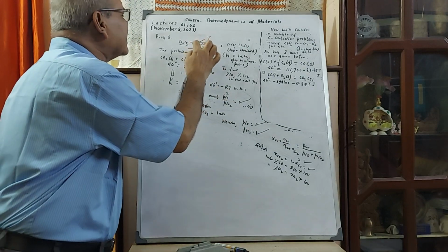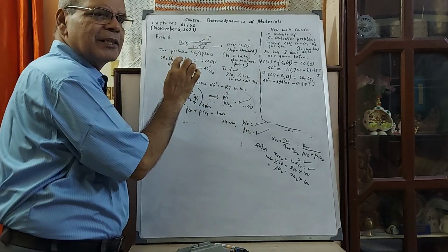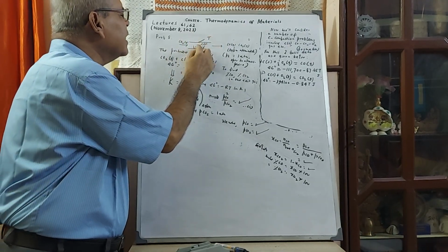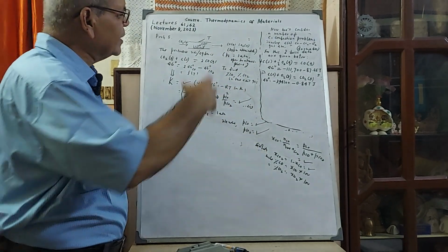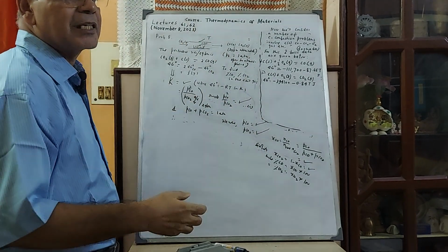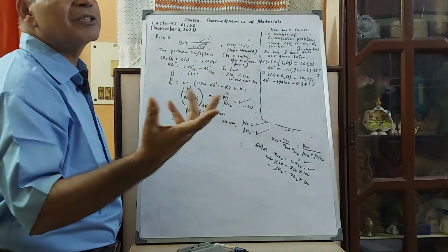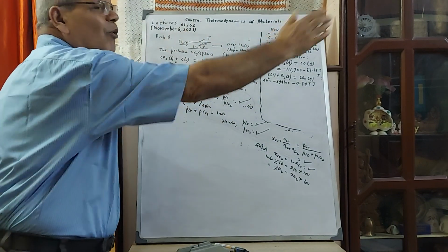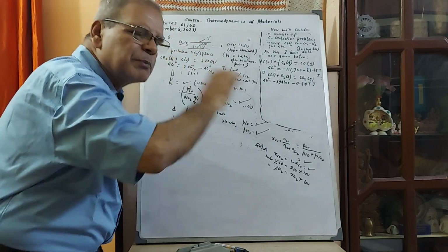So suppose it has attained equilibrium somewhere in the middle of the path. Then what will it do after that? Again, there is a little path left. Carbon is there, and the CO2 CO equilibrium mixture will pass over it. No change. It has already attained equilibrium with respect to carbon, so no more reaction. It will just go over it. Or it may be possible it attains equilibrium just before exiting.